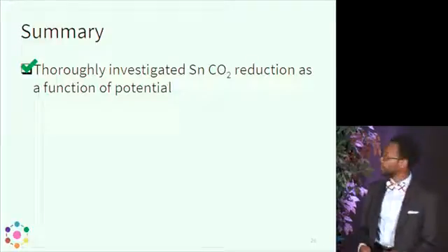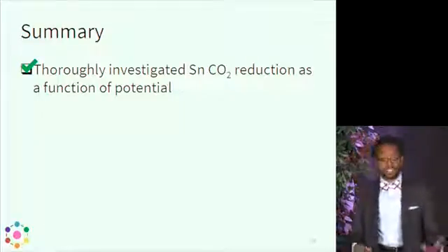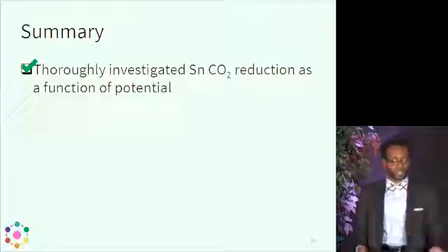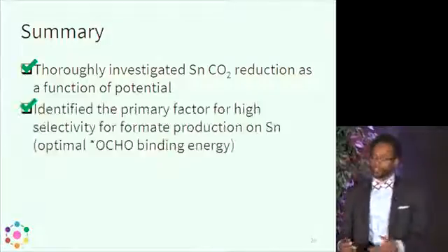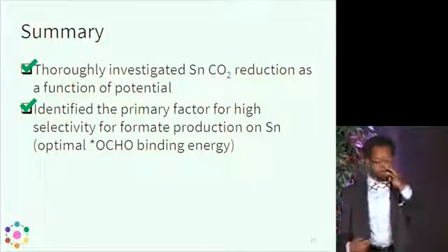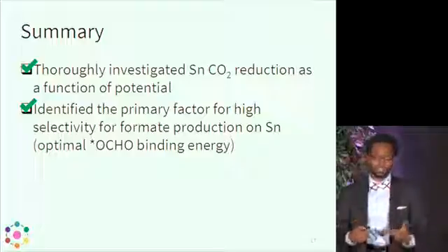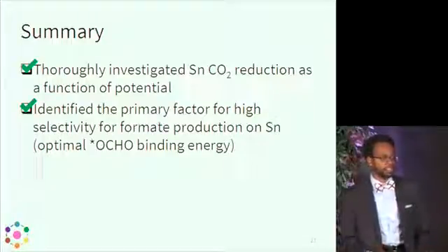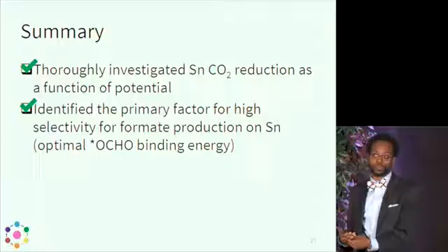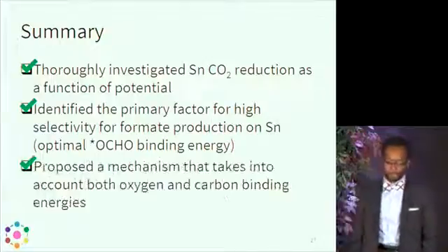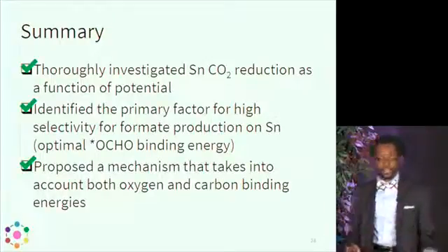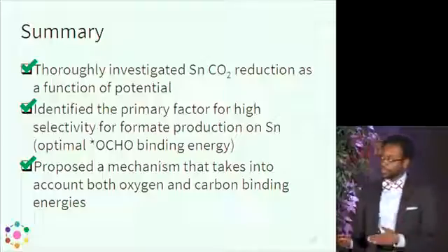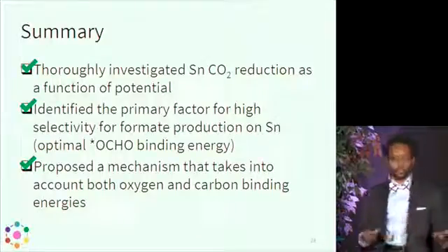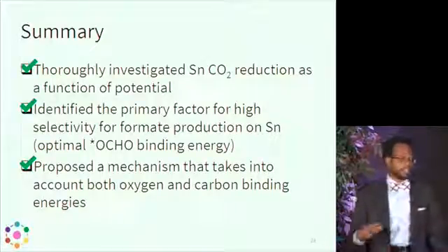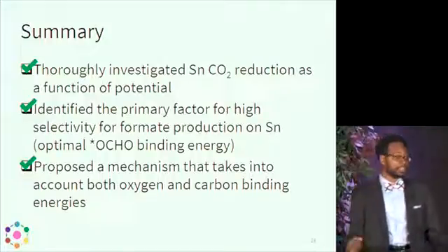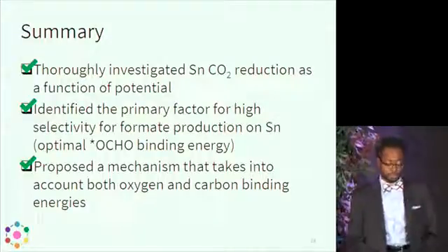And so just to summarize, we were able to thoroughly investigate tin for CO2 reduction as a function of potential. We were also able to then identify the primary factor for high selectivity on tin electrodes and really answer that question of why tin is so good at making formic acid for CO2 reduction. And of course, the key being that OCHO binding mechanism. And then also, we were able to propose a mechanism that encompasses both carbon monoxide and formic acid production as a result of CO2 reduction.